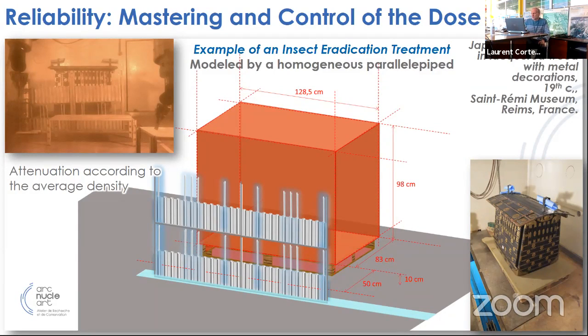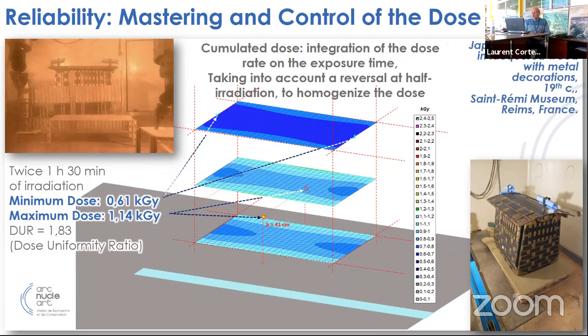For instance, always with this Japanese palanquin, we can model the palanquin by a homogeneous parallelepiped to set the condition of irradiation. So we can calculate the dose rate and then integrate the dose rate and the exposure time, taking into account a reversal at half irradiation. And not surprisingly, we have the maximum dose in both front side and back side that are symmetric because of the reversal, and minimum dose on the middle,